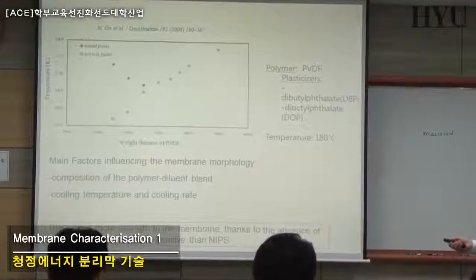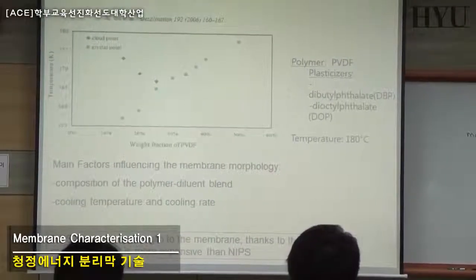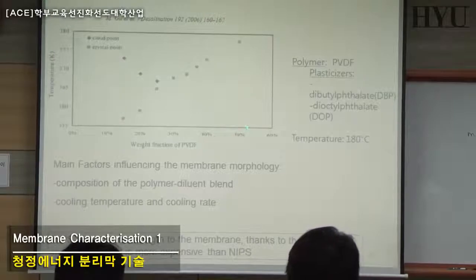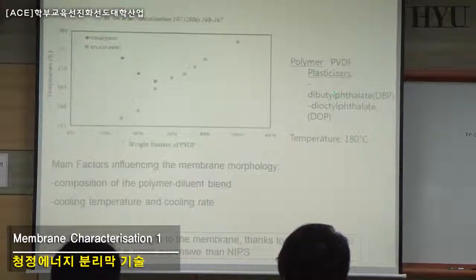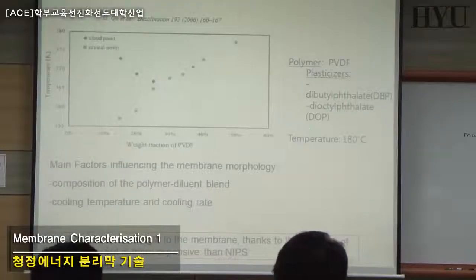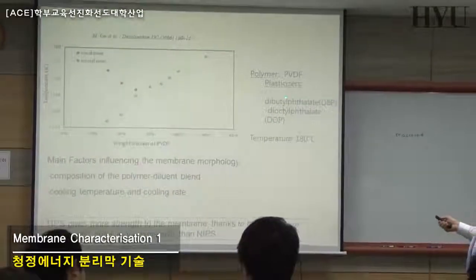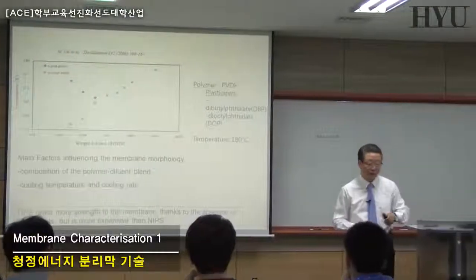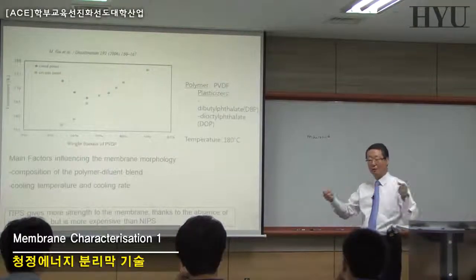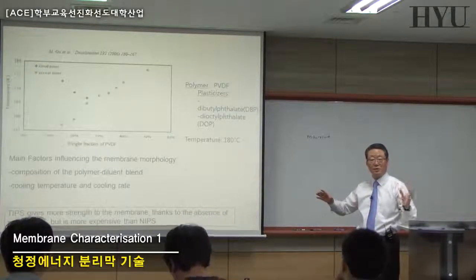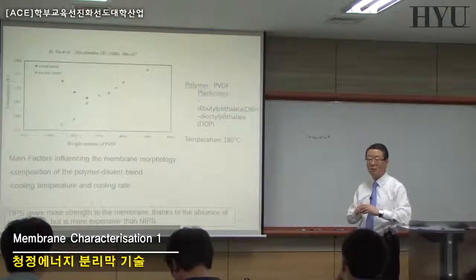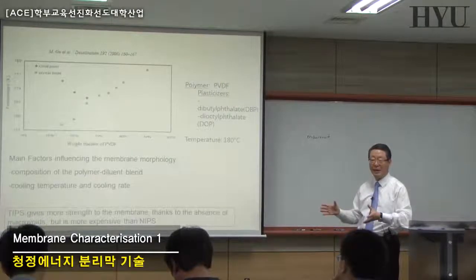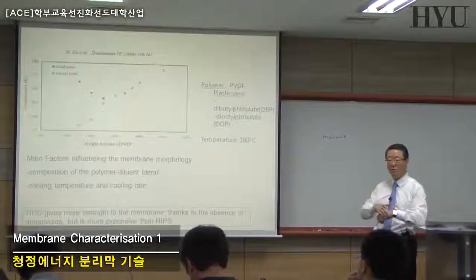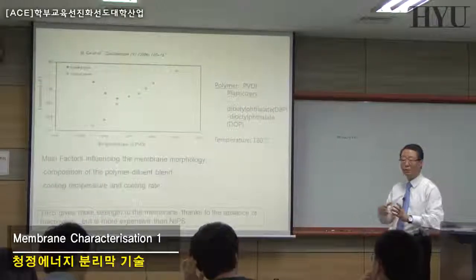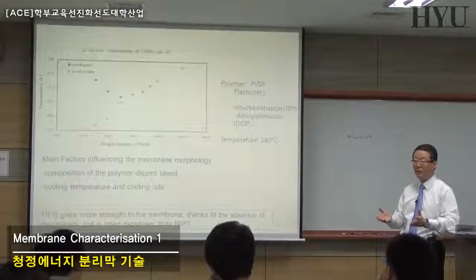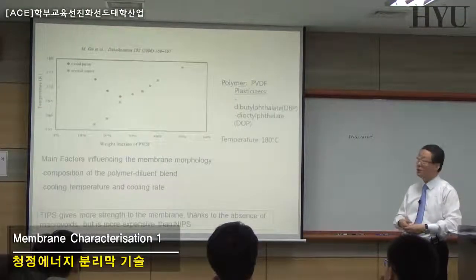Now, we can have the point where you form the crystals, by changing the polymer concentration in the latent solvent, in this case DOP, dioctyl phthalate. Dioctyl phthalate is regarded as a plasticizer in making your PVC, polyvinyl chloride, films and pipes. This DOP is, however, very toxic and carcinogenic, and it's banned in many parts of the world. But still, the DOP could be used in many countries as well, in making membranes and films.